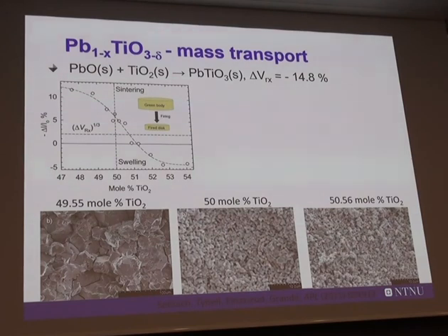So in the DFT calculation I showed for PCT, they are similar to many other materials. But we just distribute the oxygen vacancy in the material. You can calculate the energy landscape of the vacancies at different sites, so you know the energy information of the different sites. And in some cases, the formation energy is so low that we will induce vacancies by an electric field. Low, just... It could be as low as 1.5 eV. Oh, okay. But it could also be as high as 5 eV. Yeah, okay.